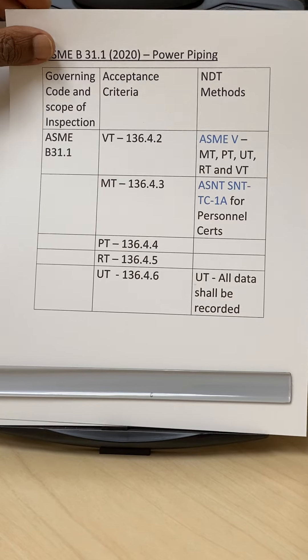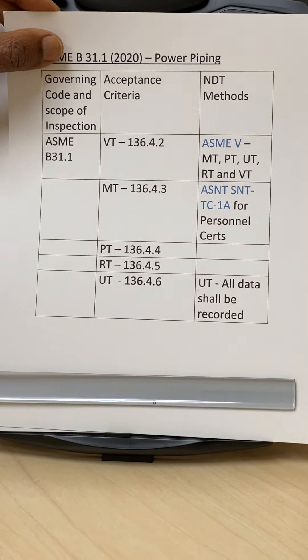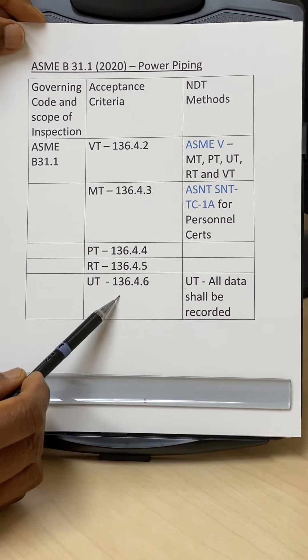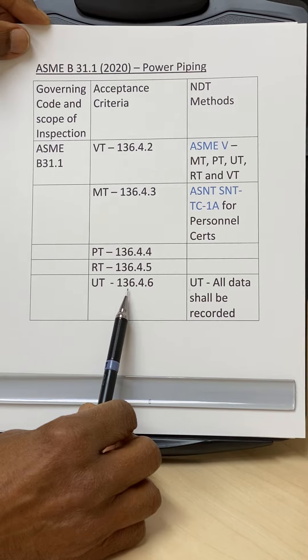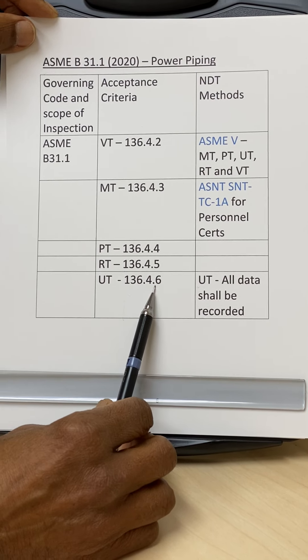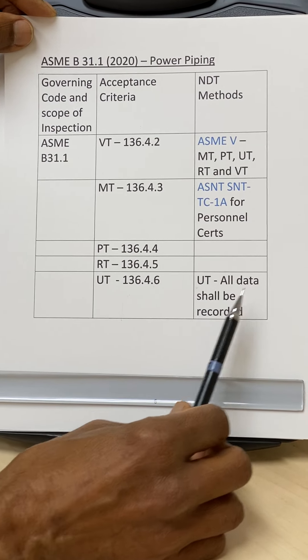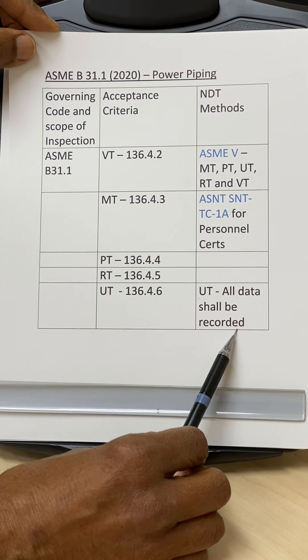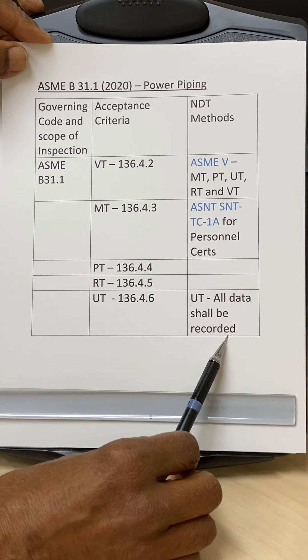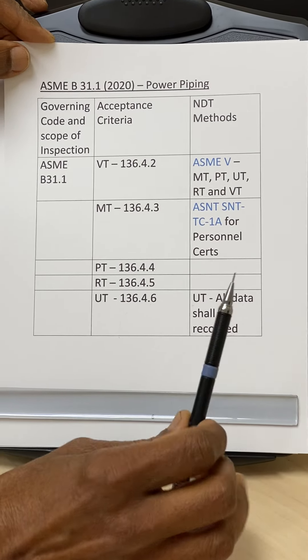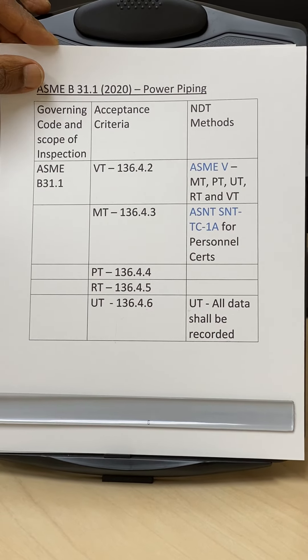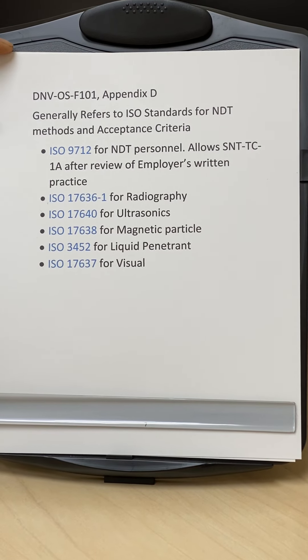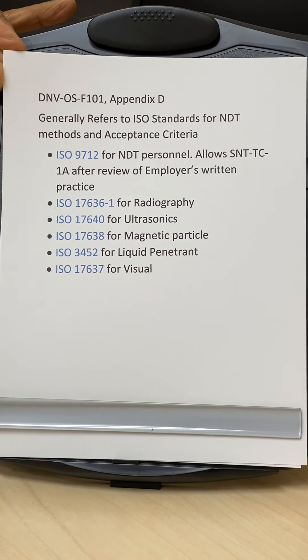There is no acceptance criteria in ASME Section 5. One important note for B31.1: if you are doing UT, the new edition states in Section 136.4.6 that all data shall be recorded — you cannot simply do manual UT on steam lines or high-energy piping and say everything is okay. That is no longer acceptable inspection practice.